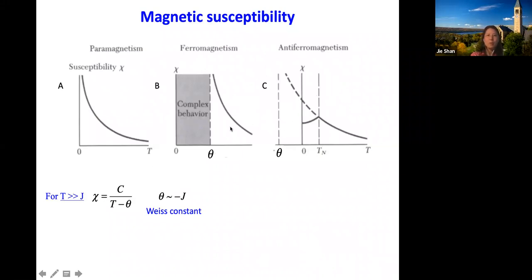This is how magnetic susceptibility looks as a function of temperature from our solid state textbook. This is for paramagnetism, and for ferromagnetism, above the Curie temperature, it follows this and then diverges at the Curie temperature. And for antiferromagnets, above the Néel temperature, you have this 1/(T minus theta) dependence. If you ignore the transition and extrapolate, it diverges at this constant, which is now negative.